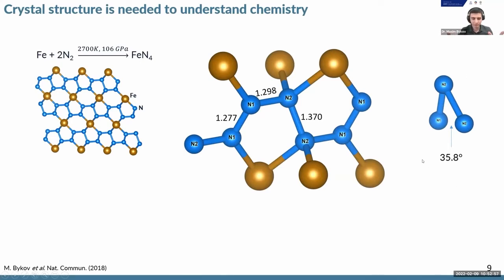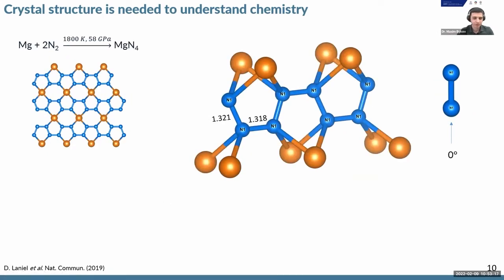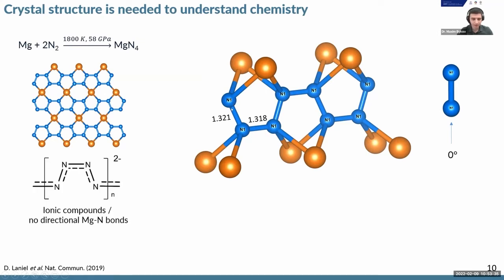Based on this crystallographic information, we could actually judge the connectivity of nitrogen within the chains. And we interpreted it as a polytetrazene chain with 1 double and 3 single nitrogen bonds within this chain. If we now compare this with the magnesium example, we see that these chains are completely planar with 0 degrees dihedral angle. And there is only 1 symmetry-independent nitrogen atom. And all nitrogen-nitrogen distances are almost equal to each other. This allows us to say that we are dealing here with polyacetylene-like nitrogen chains with a full pi electron conjugation within these chains.